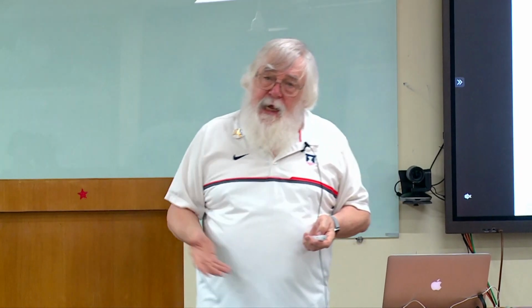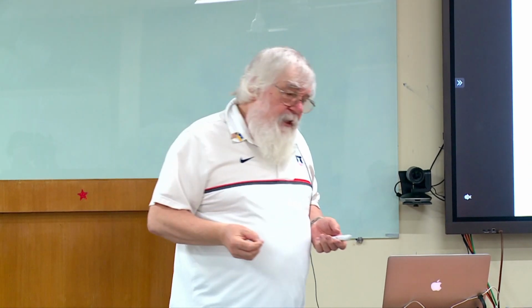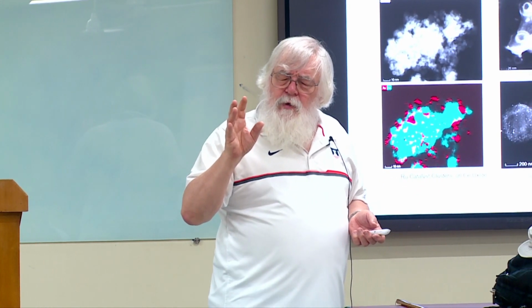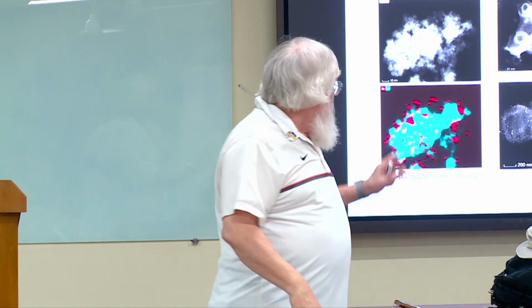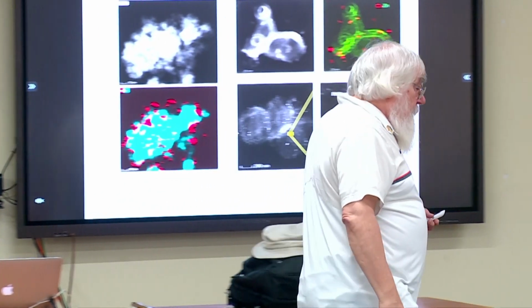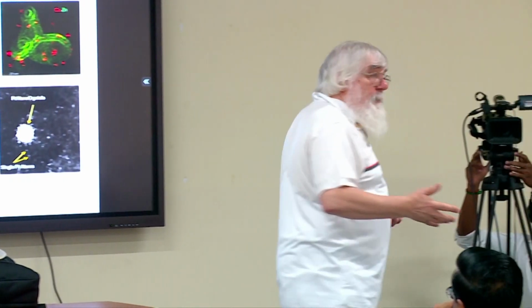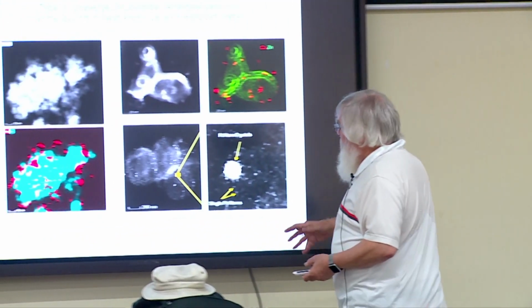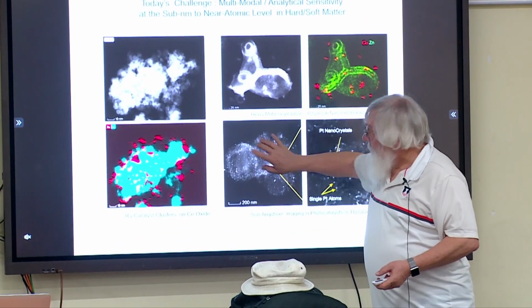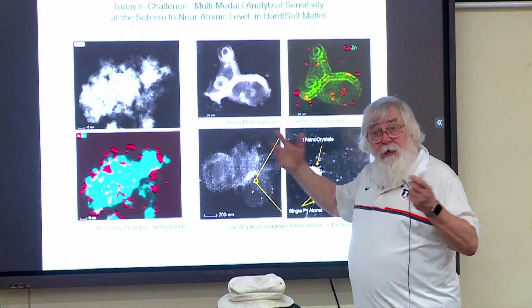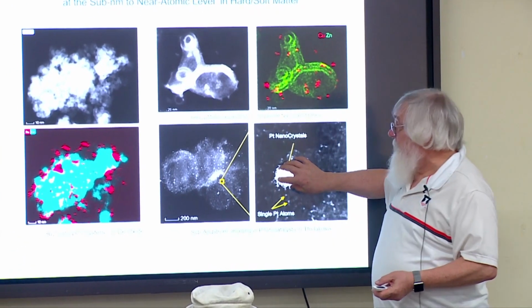What we want to do is enhance the productivity of it. We found out that if you add noble metals, in this case platinum, to the thylakoids, that the enhanced catalytic activity happens. Well, where does it go? Well, we see lots of white dots again. That we assume is platinum. Well, yes, can we see the platinum nanocrystals?